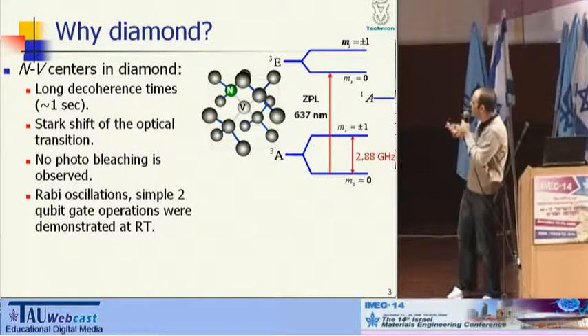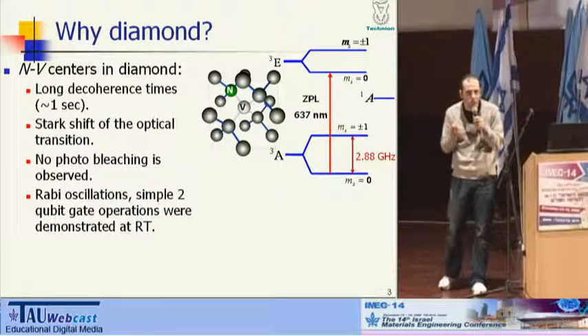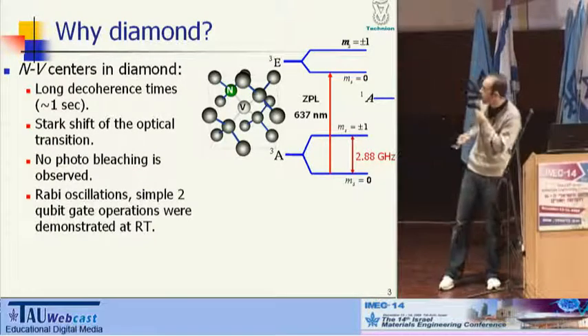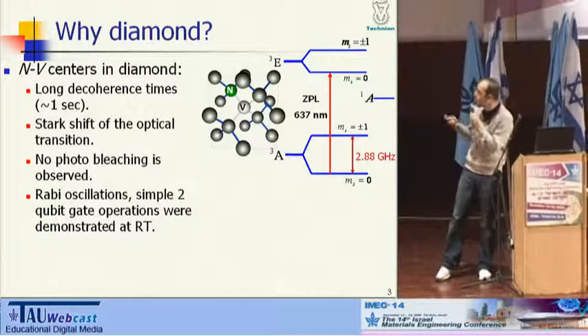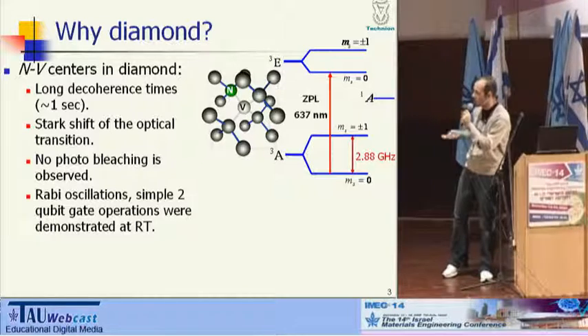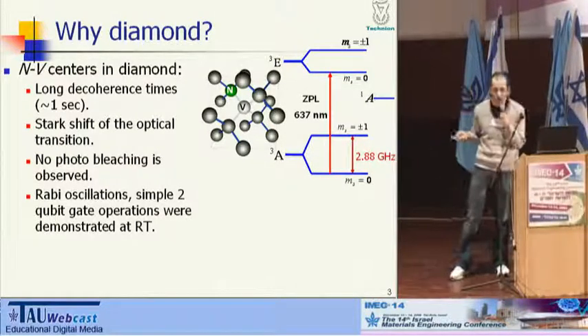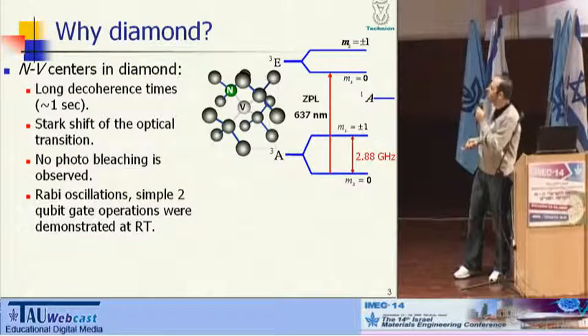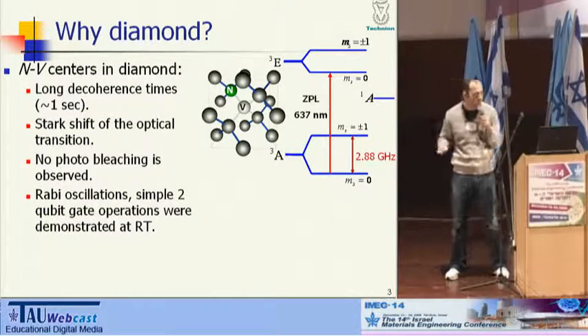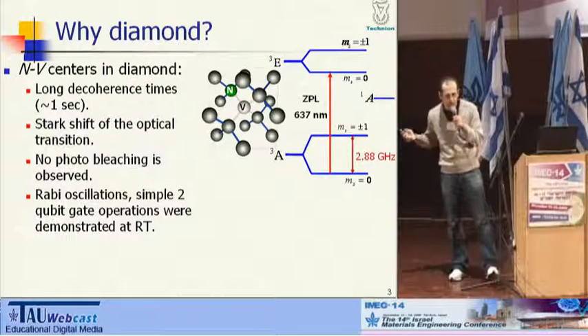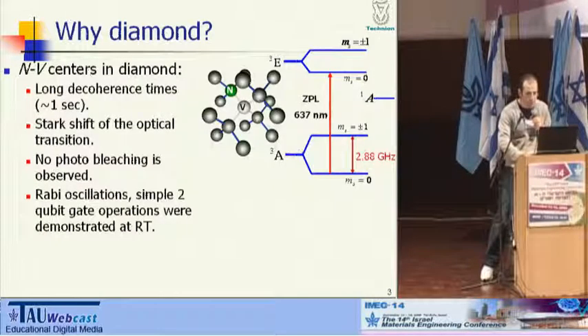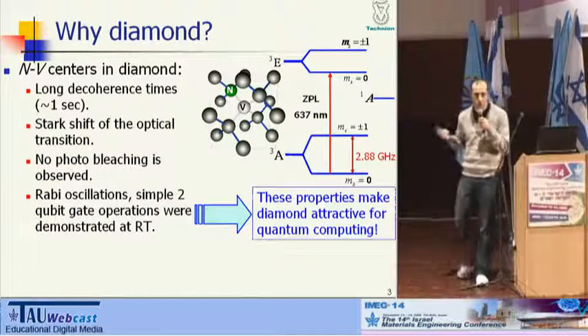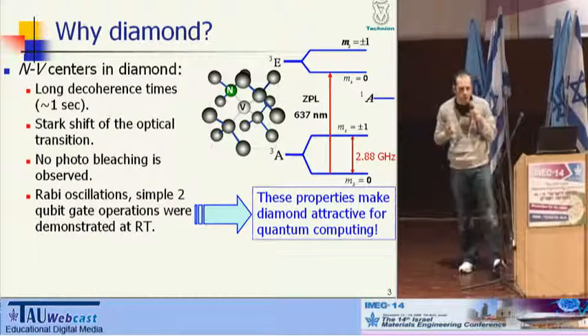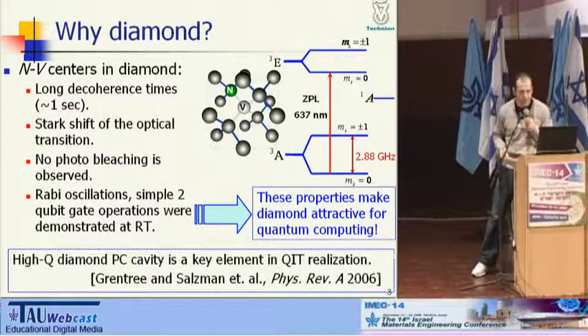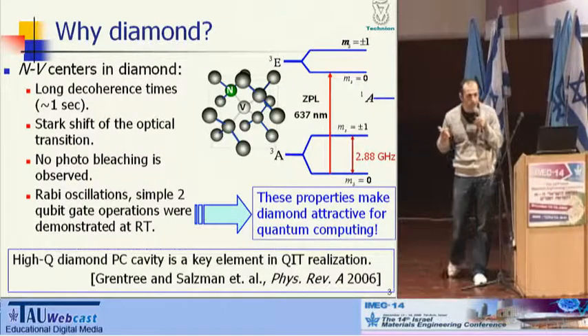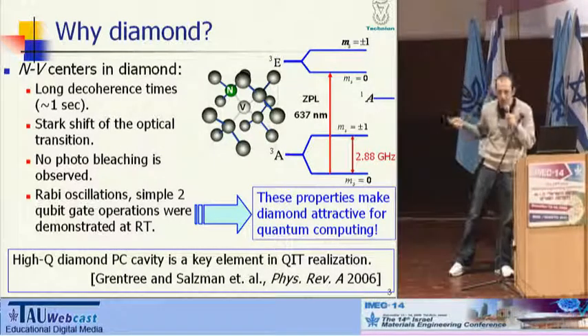All these properties allow us to measure a single spin at room temperature, which is, as far as I know, the only system where it is possible. Moreover, the NV center has other extraordinary properties, such as very long decoherence time and Stark shift of the optical transition. No photobleaching in the NV center occurs, and Rabi oscillation and simple 2-qubit operations were demonstrated at room temperature. All these properties make diamond very attractive for quantum information technology. Moreover, I'll try to persuade you that incorporating this NV center in a high-Q diamond photonic crystal nanocavity will allow the realization of large-scale quantum computation.